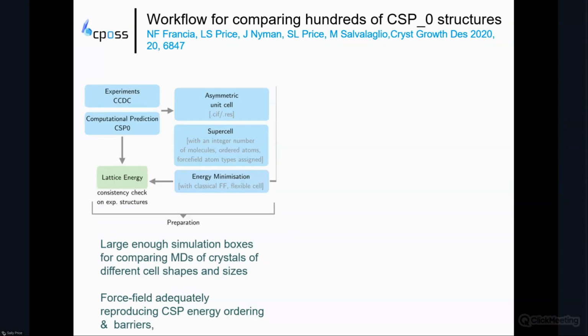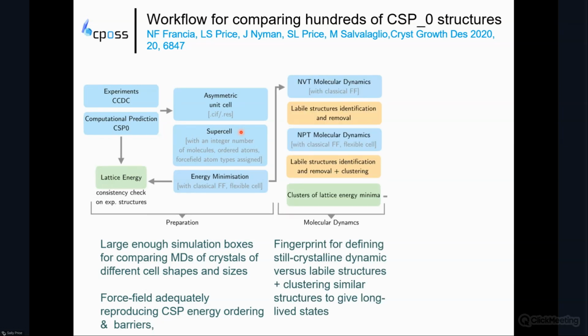And Matteo Salvalaglio, my colleague, has been developing this with us. The input to his workflow is to take our CSP structures and any extra experimental ones there are and set up large enough simulation boxes for comparing the molecular dynamics of crystals of very different cell shapes and sizes. And the first test, because the molecular dynamics, to be able to do it efficiently, has to use a force field, is to check that the force field is adequately reproducing the CSP energy ordering and barriers that it's worth going ahead. But then you can do your molecular dynamics, first of all fixed cell, and then allowing everything to relax to see which structures melt and which structures coalesce to be the same.